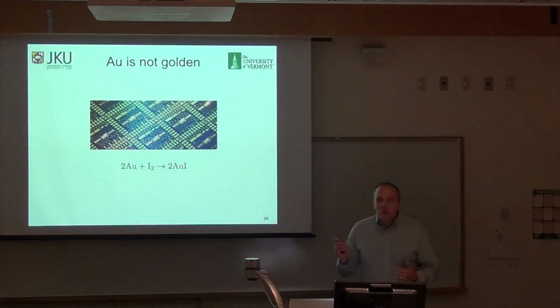What we've been using, what everyone's been using up to this point, is gold. Most of us device people think, oh, gold, it's stable under everything. But the one thing that you can use to etch gold in the semiconductor industry is iodine. Here we have this lead iodide crystal where iodine is leaching out of it due to water vapor, producing the one thing that etches the gold. So this is a real catastrophic problem - it causes the gold, where the bubbles come out, to delaminate, and then it causes more water to come in, and it catalyzes the death of these solar cells.